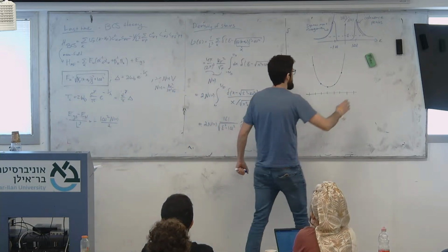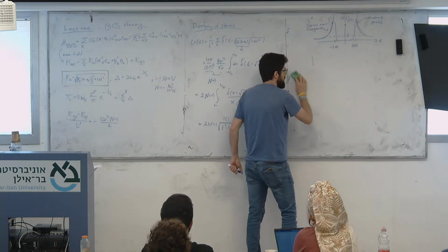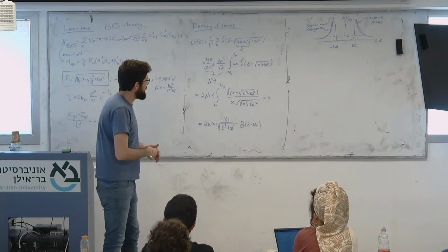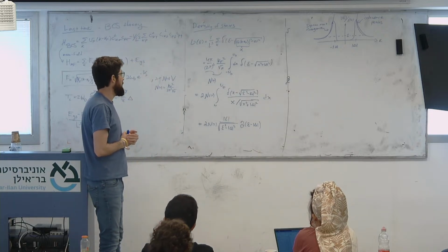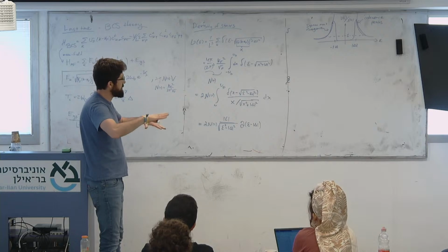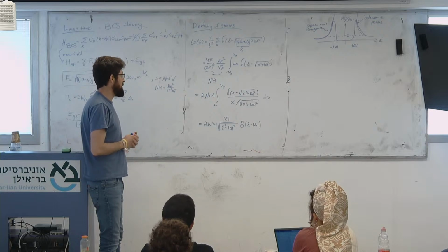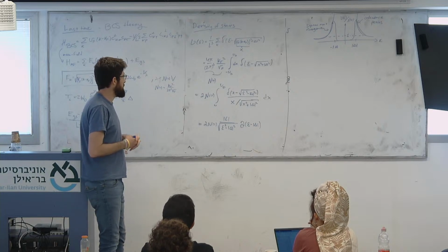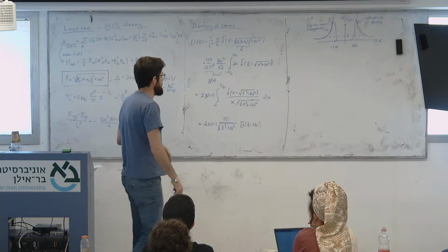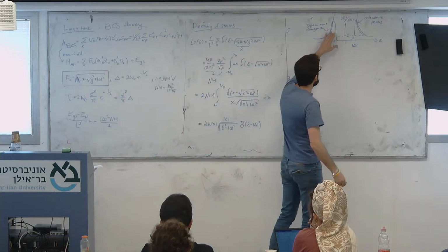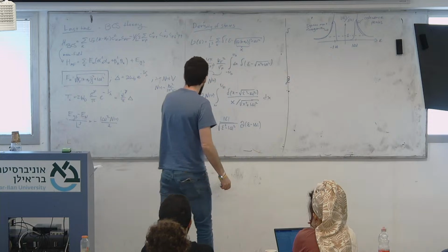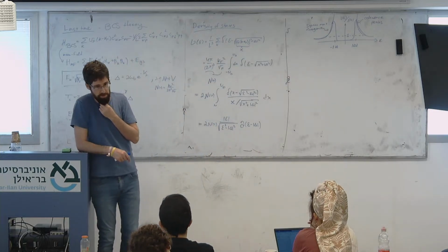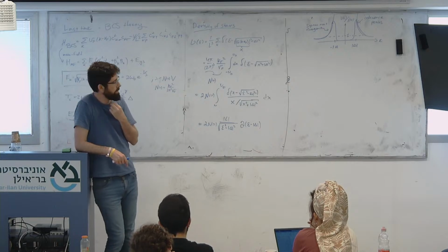I won't have time this year to teach it, but there is an Abrikosov-Gorkov theory. If you put in pair breaking disorder, then you would smear the peaks as well. You can also have variations in Tc in the sample that will cause a smearing of this at finite temperature. So there are all sorts of things that can smear these coherence peaks. Also, you can write with impurities. Yeah, that's what I was saying. Disorder. Impurities is disorder. Okay?